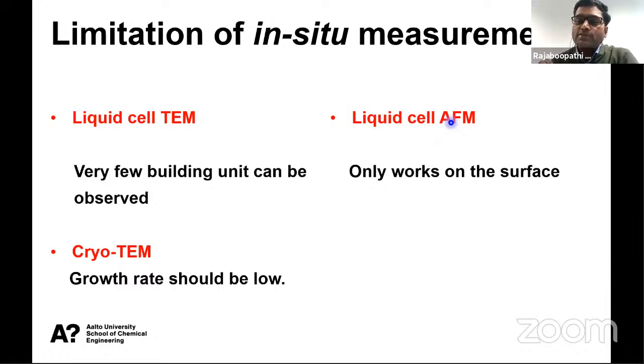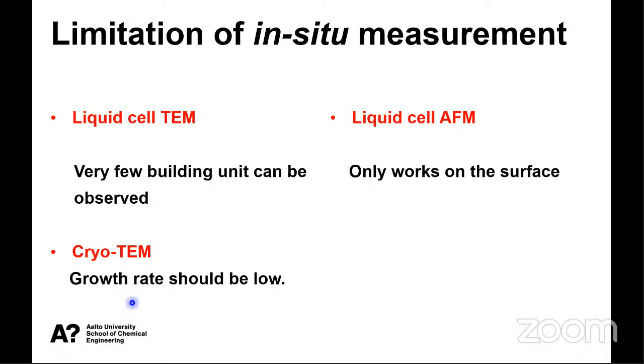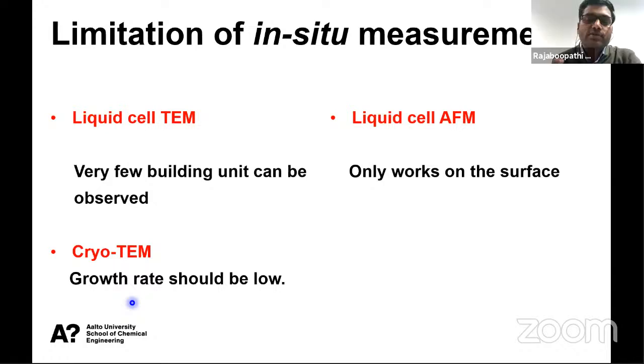But AFM is mostly good for solid samples. When you use a liquid, maybe we cannot get a high resolution image. And also cryo-EM: in cryo-EM we can freeze the solution to see what is happening in the solution. But the crystallization process is very fast. Within 15 seconds, within 15 minutes, it will complete the process. So you need to harvest at different stages to see whether it is oriented attachment or mesocrystals.